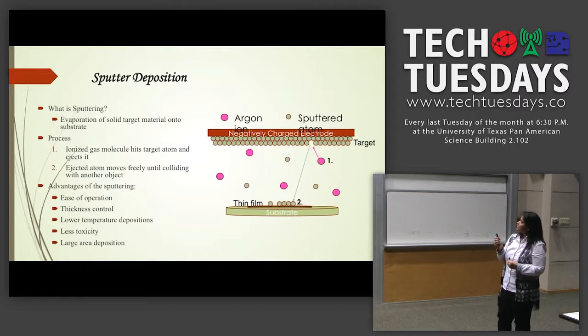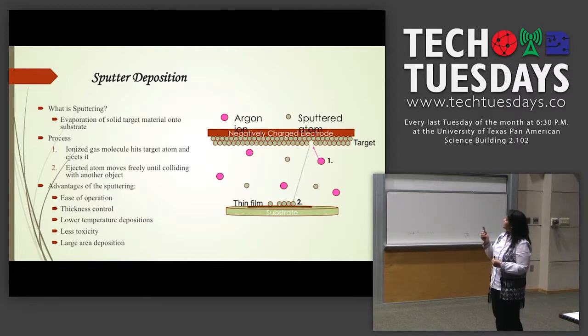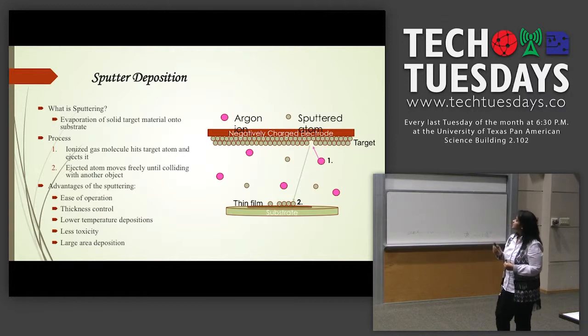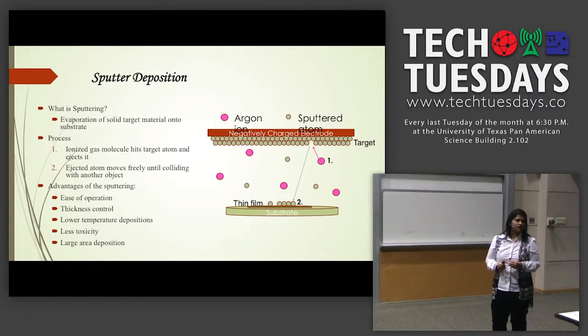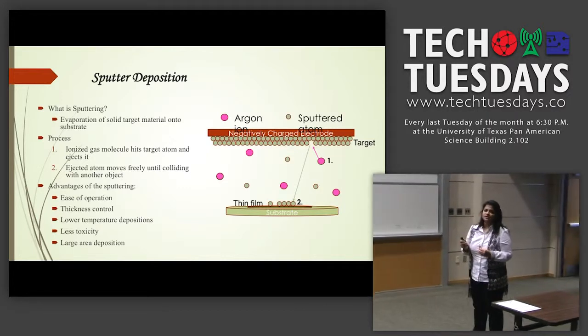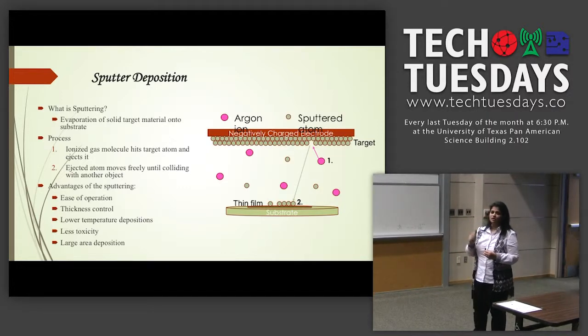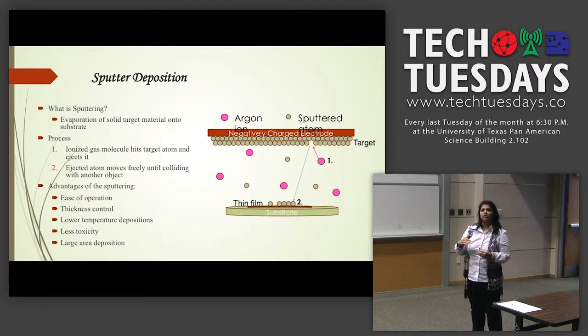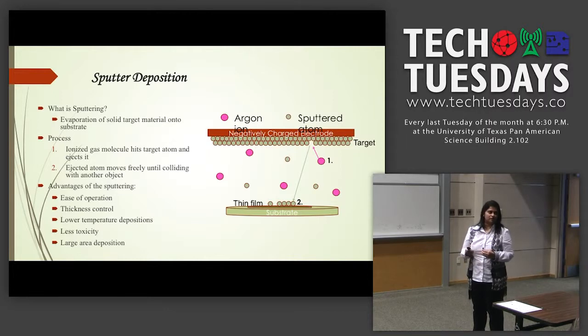The sputtering process works as follows: the top part is the target and the bottom part is the substrate. We introduce a process gas — usually an inert gas, argon. We apply voltage to energize the particles. The energized particles hit the target and dislodge atoms, allowing us to grow atom-by-atom layers at nanometer thickness.